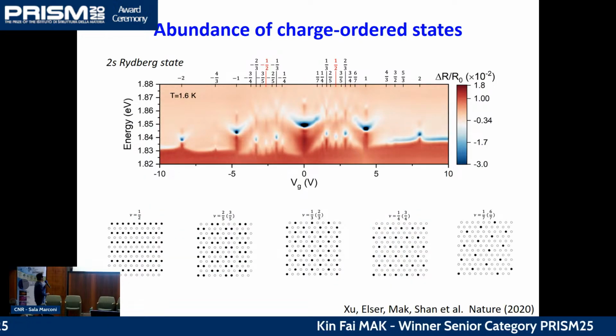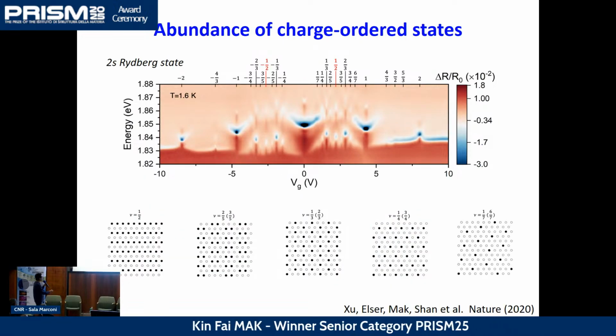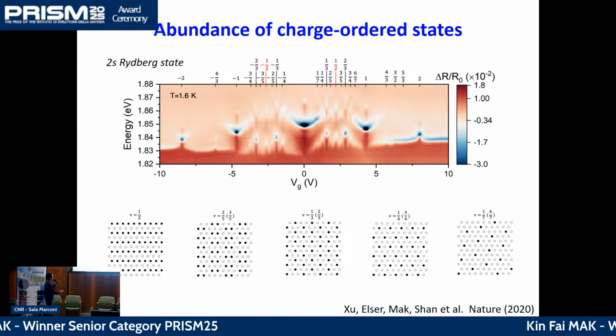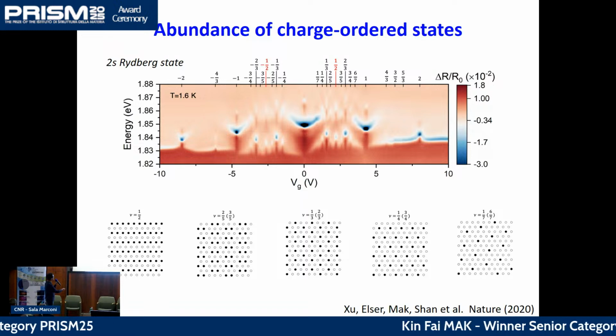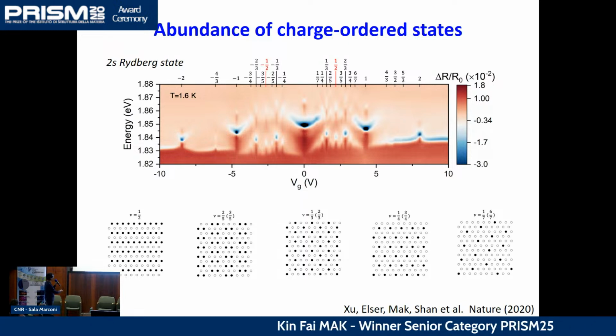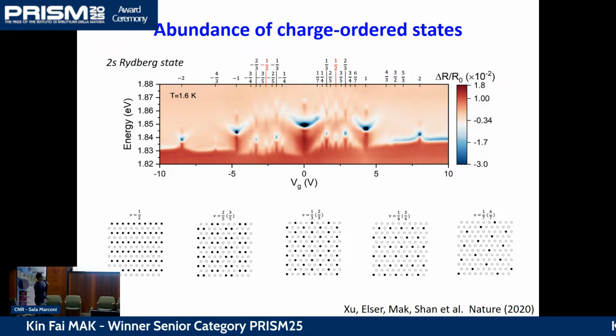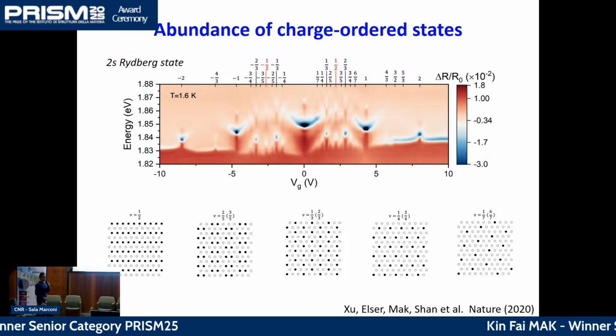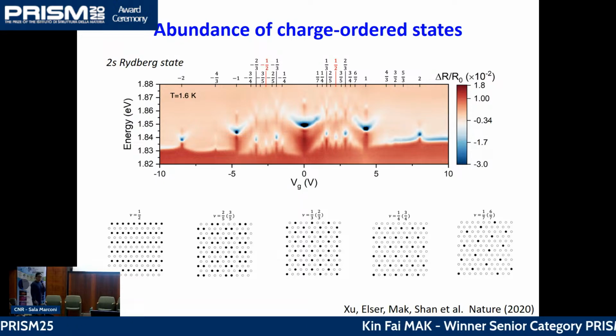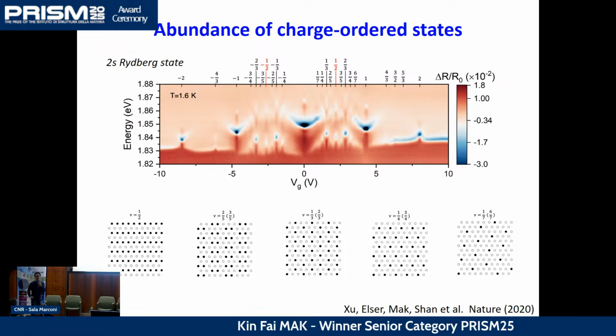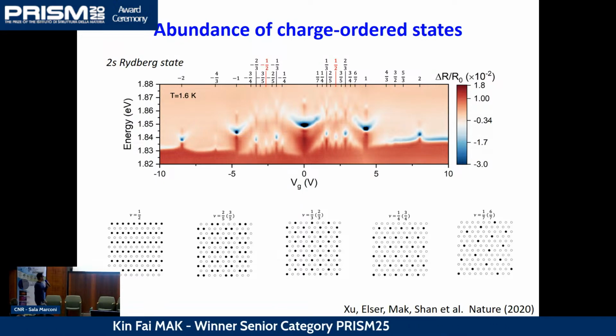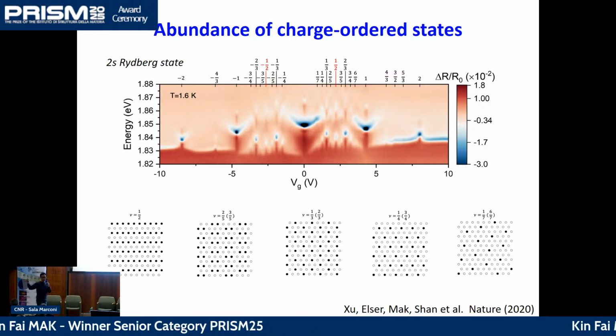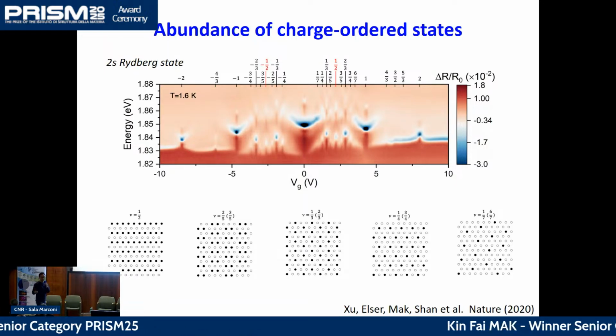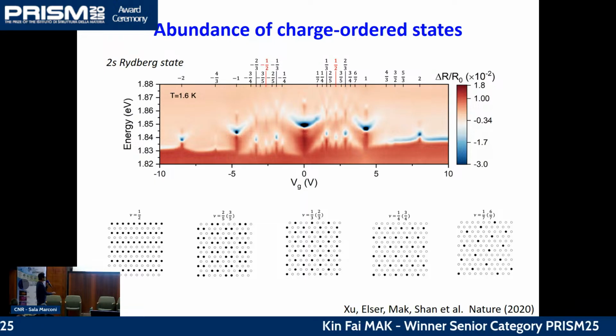Okay. So I think we have a pretty good understanding of what's happening at filling factor 1, filling factor 2, and -1 and -2. Very briefly, you can also see that there are lots of insulating states with fractional fillings, for instance, 2/5, 1/3, 2/3, 1/4, et cetera. Each of these bright peaks here is one of these insulating states. What's happening is, again, the strong Coulomb repulsions between the electrons do the magic. Because of the longer range Coulomb repulsion, the electrons self-organize into a crystal structure. These are called Wigner crystals.